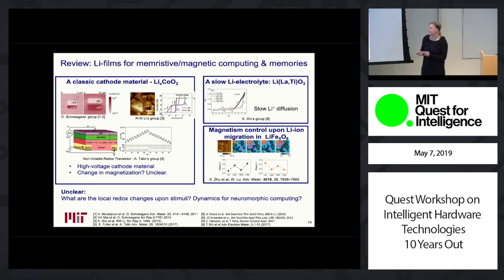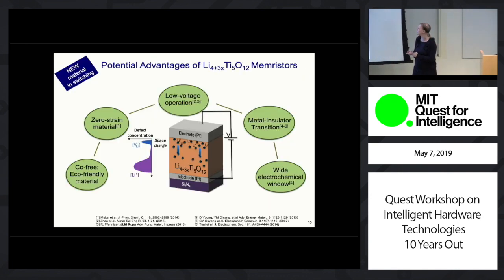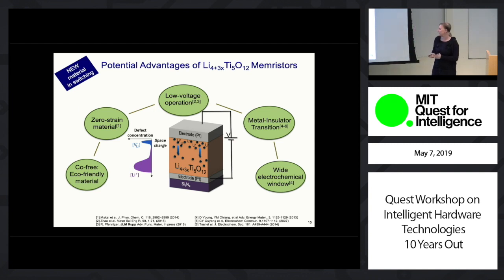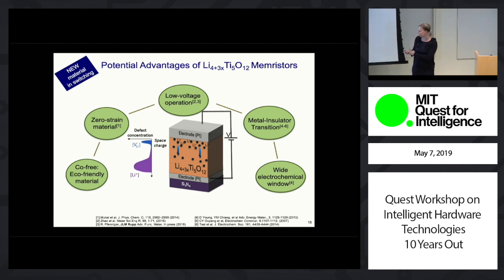Now that is all very nice. However, these materials may not be the most ideal ones because you still need a lot of energy to move lithium in lithium cobalt oxide, and also it's not very environmentally friendly if we think about the cobalt crisis. So what my team proposes is to make the first lithium titanate memristor, a material that is actually a classic battery anode, where you need a very low energy to use the lithium, by a valence change, to activate the titanium and have very fast dynamics in the metal-insulator transition. The other thing that's interesting is that lithium and titanium are readily available.